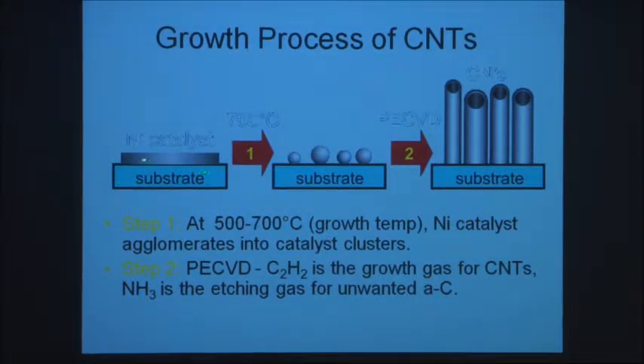So you start with the substrate. You might put a barrier layer in here, but whatever else, you put the nickel catalyst. You then heat up the nickel catalyst in the deposition chamber at typically between 500 and about 1,000 degrees C. And the nickel catalyst breaks up into little balls. You get these little balls on the surface. From being a thin film, you now get the nickel balls. You then strike the plasma, add the carbon-containing gas, which could be C2H2 or CH4 or whatever, and some etching gas, ammonia or hydrogen typically, and that etches away any unwanted amorphous carbon, and the carbon itself is there to make the carbon nanotubes. It's in essence quite simple. In practice, it's not so simple. So, substrate, heat up a thin film. Thin film produces little balls of catalyst. That catalyst can then be used to produce nanotubes.